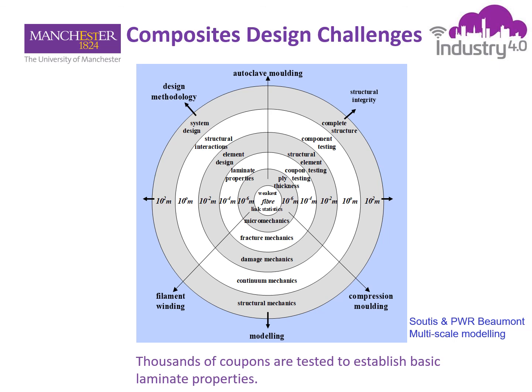And those models, they need to take into account the original state of the component, accounting for the manufacturing method used to fabricate the part. Because the autoclave molding or filament winding or compression molding, they introduce different type of defects that we need to take into account in our damage mechanics analysis in the effort to estimate the strength, stiffness, long-term performance of the composite.